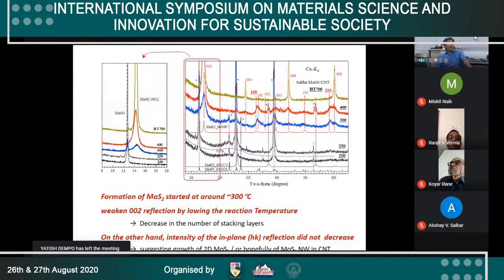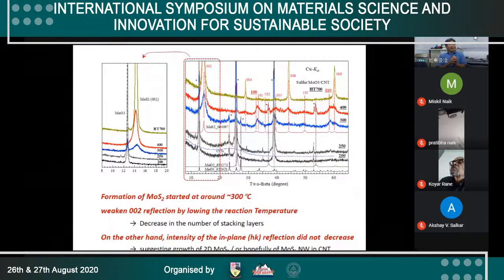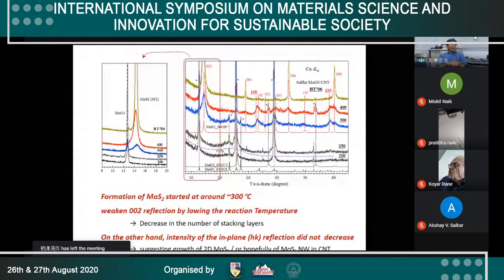molybdenum disulfide formation occur. And then when we see there are two reflections at the lower side, when we increase the temperature, in such a case, the reaction starts rapidly, but at low temperature, slowly is progressing. And the interlayer stacking, we can suppress at the low temperature synthesis. Okay, next slide, please.